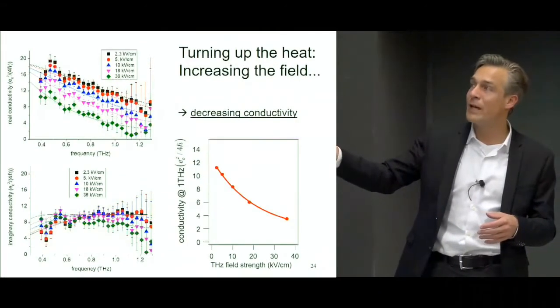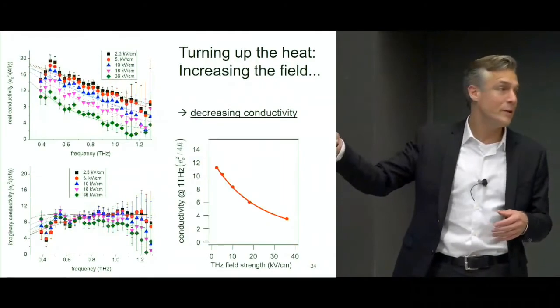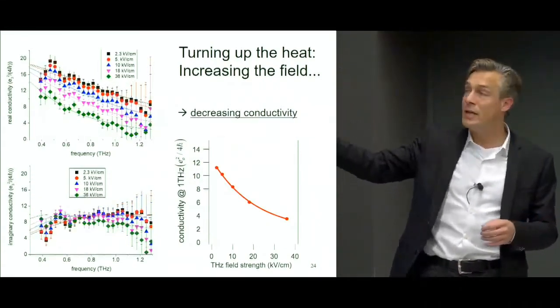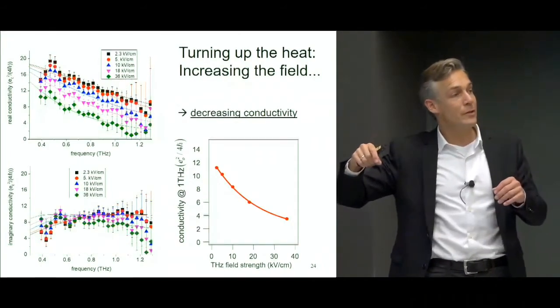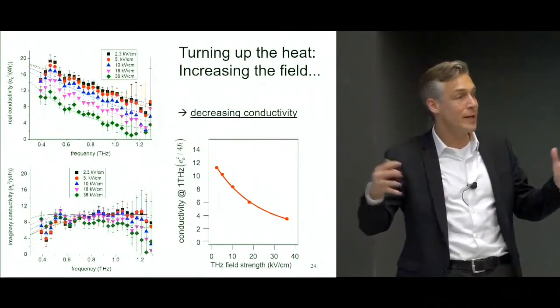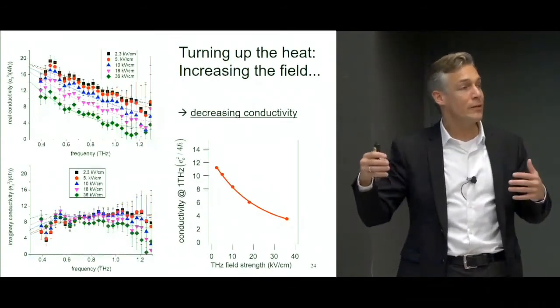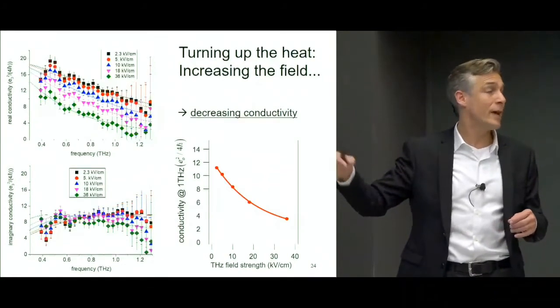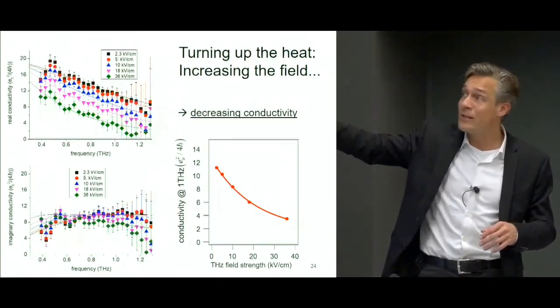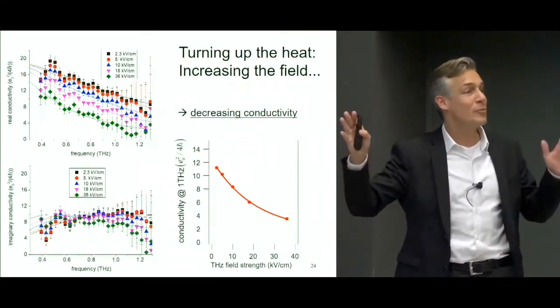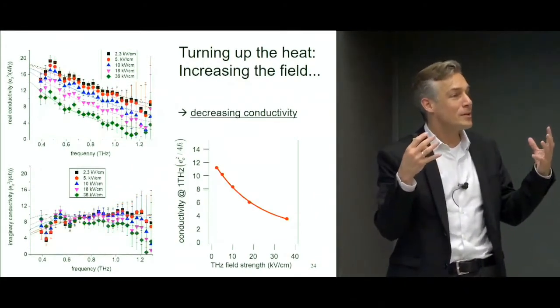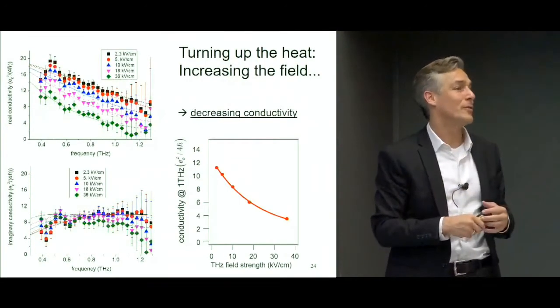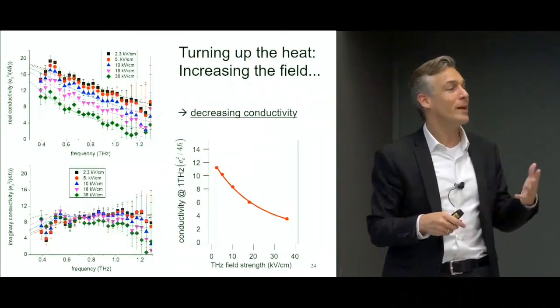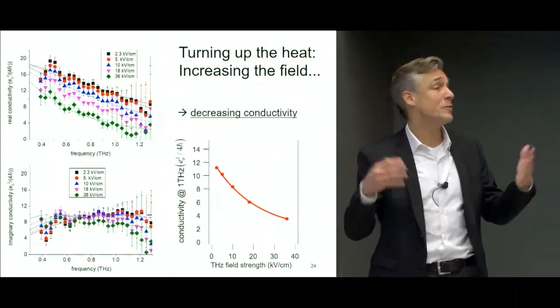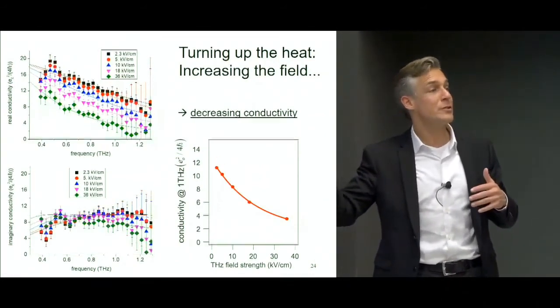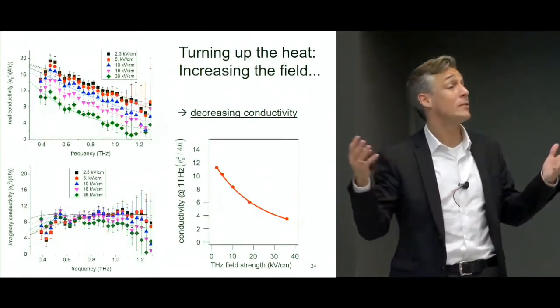And related to that, what you can see here is that the DC conductivity is fixed, it's pinned. And as you heat up the electrons, you have spectral weight conservation, so you cannot get additional overall absorption, and you get extra interband transitions at much higher frequency. And so the spectral intensity has to drop here. So the conductivity has to drop. This is one way of explaining it, but I do not have a compelling physical picture of why that is. So in a metal, of course, you heat it up, the scattering rate increases, the mobility decreases, life makes sense. In graphene, the band structure is such that you heat it up, the scattering rate decreases, and yet the conductivity decreases.